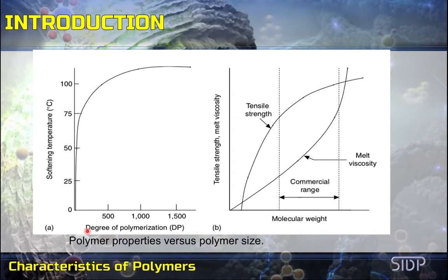The dimer of polyethylene is a gas, but oligomers with a DP of 3 or more are liquids, with the liquid viscosity increasing with the chain length. Polyethylenes with DPs of about 30 are grease-like, and those with DPs around 50 are waxes. As the DP value exceeds 400, or molecular weight exceeds about 10,000, polyethylenes become hard resins with softening points about 100 Celsius. The increase in softening point with chain length in the high molecular weight range is small.